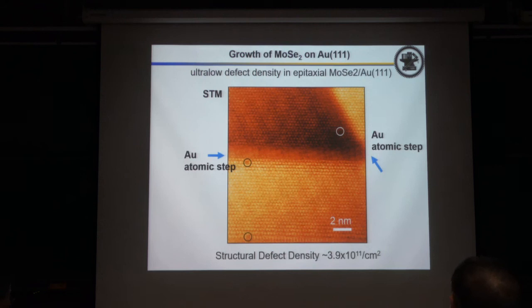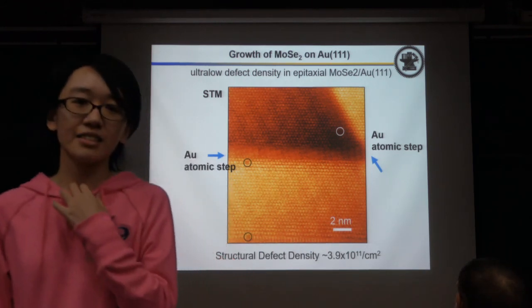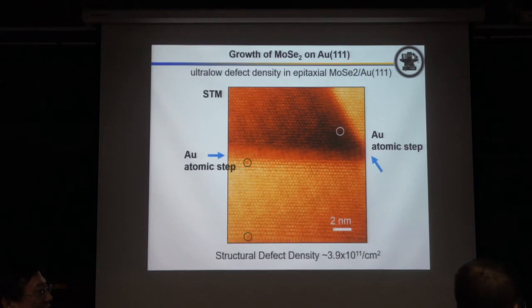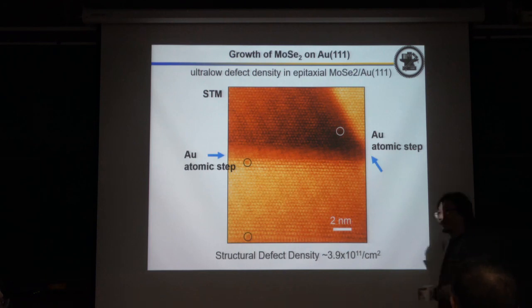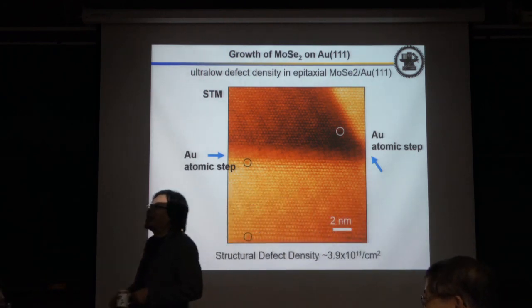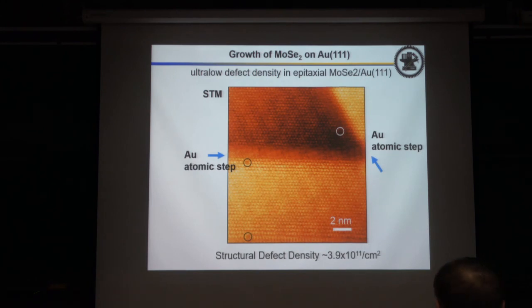Well, in this case, I agree with the speaker, because he rightly said that gold is metal and DFT predictions are quite good. But it happens that this Moiré system is a semiconductor, and it's well known that current DFT calculation cannot give a correct band gap. And I think the potential exciton is due to the band gap. So they still have some limitation. According to my understanding, DFT cannot predict the band gap at any scale.